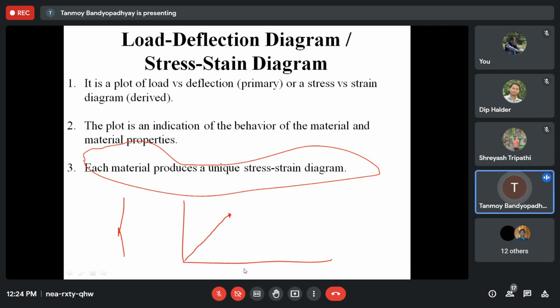Once you cross the elastic limit, you can see the curve goes to a lower yield point, and then there is an ultimate load and a breaking load. You can see that you haven't increased the force too much beyond the elastic limit, but you are getting a higher amount of deformation in the specimen. The material has become plastic. That means even a small amount of force causes a very large amount of deformation in the specimen.